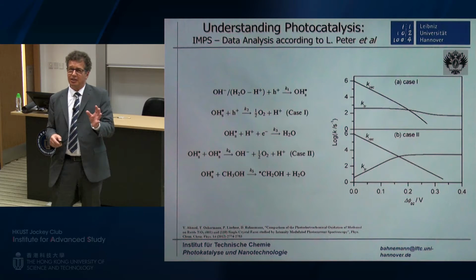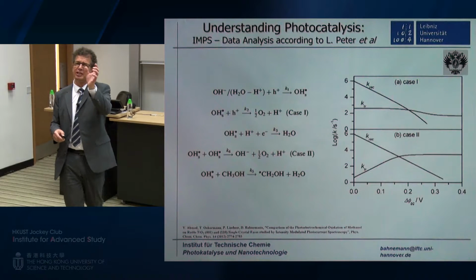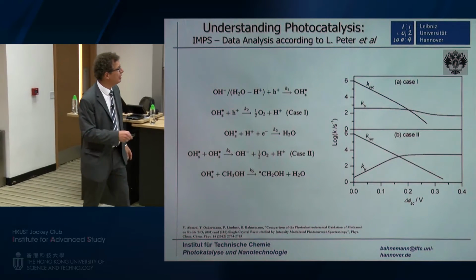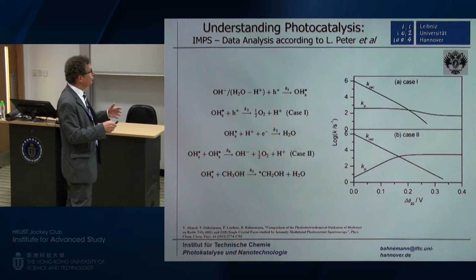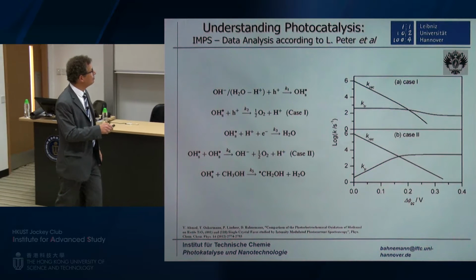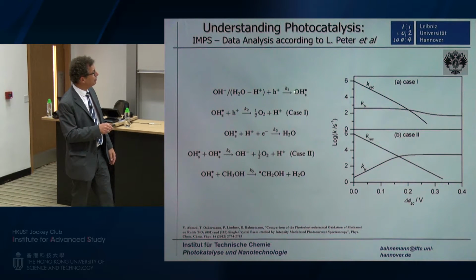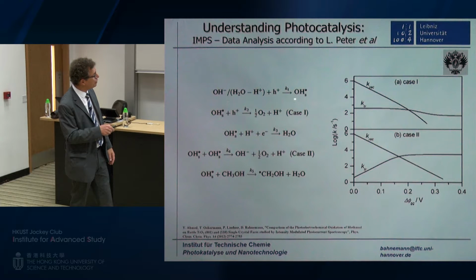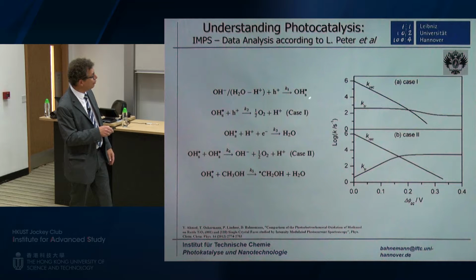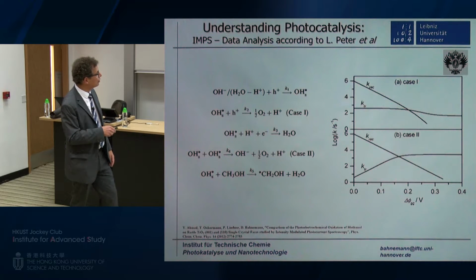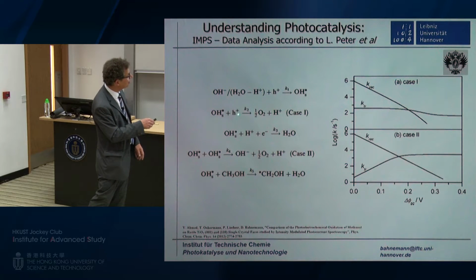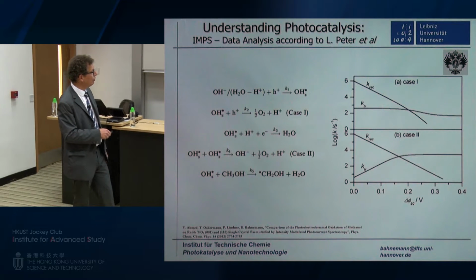And the interesting thing, or one mechanism that he has looked into, is the oxidation mechanism of water. If you think, how is water oxidized? When is the oxygen-oxygen bond formed? And you can envisage many mechanisms, but let's just look at two different mechanisms here. You can envisage first the oxidation of a surface hydroxyl group forming a surface hydroxyl radical, which is then further oxidized by a second hole, and then you get the generation of oxygen.